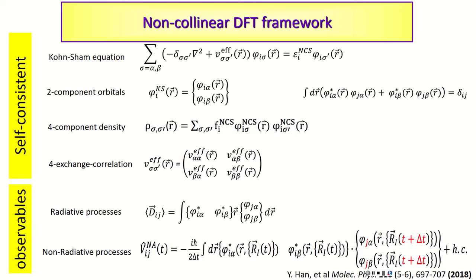And generally, one needs to go from just two components, spin up and spin down. One needs to consider them not as an independent set of orbitals, but as connected spinors. And then all things, including the potential, all operators start having four components, right? If you do not have spin orbit, it will be only diagonal components. If you allow them to mix, there will be off-diagonal components. And one needs to make appropriate adjustments to the oscillator strength for optical properties and for the non-adiabatic couplings. So there will also be traces of the fact that orbitals are spinors rather than two-component spinors.